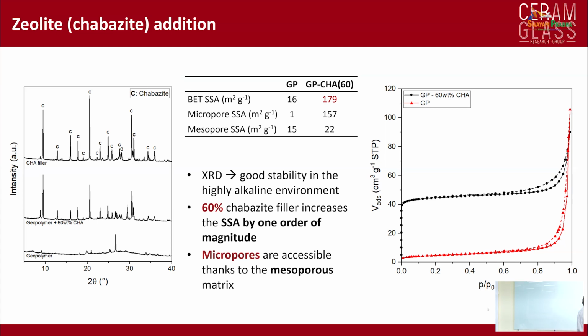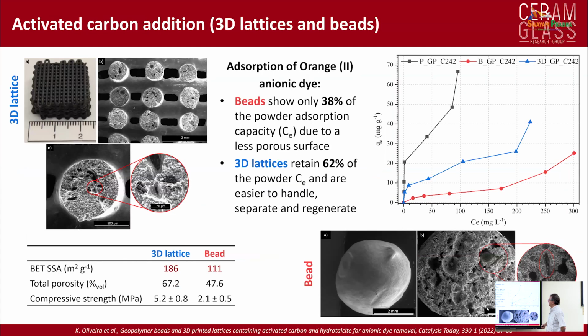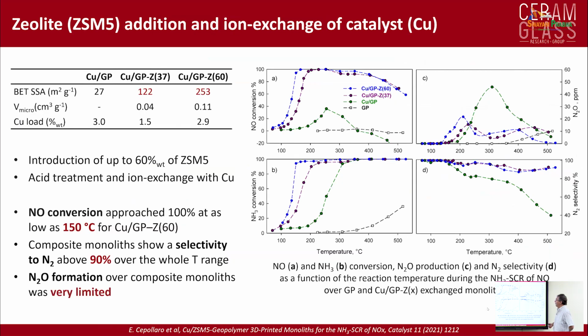And you can see that the chabazite was not decomposed in contact with the geopolymer. If this is the base geopolymer, by adding chabazite we have gained all these micropores, and therefore we have a much higher specific surface area. We added also activated carbon, and we compared the behavior of geopolymer microbeads with 3D lattices, and the behavior was better for the lattices with respect to the microbeads, or with respect to the geopolymer by itself. We also added the ZSM5 zeolite.